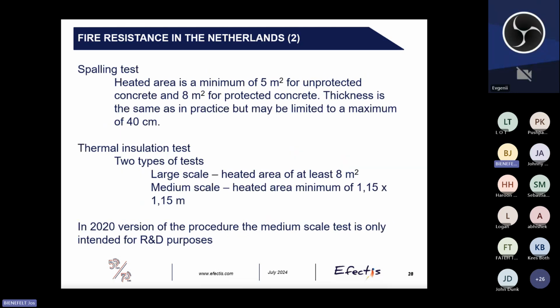When looking at the spalling test, a heated area of a minimum of 5 square meters is required for unprotected concrete and 8 square meters for protected concrete, so concrete protected with a PFP system. The thickness of the concrete slab or lining should be the same as in practice, or maybe limited to 40 centimeters.